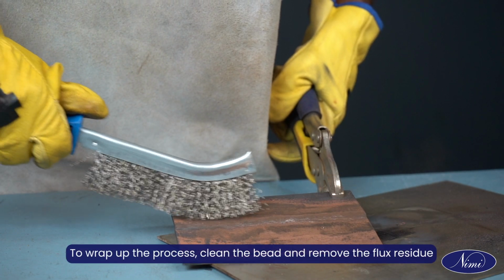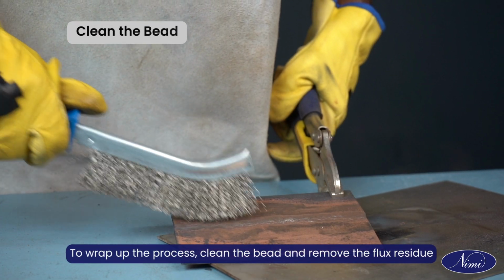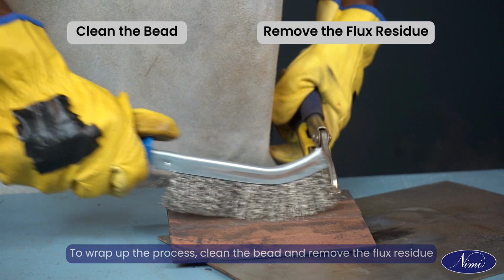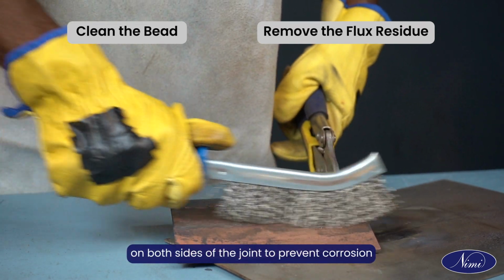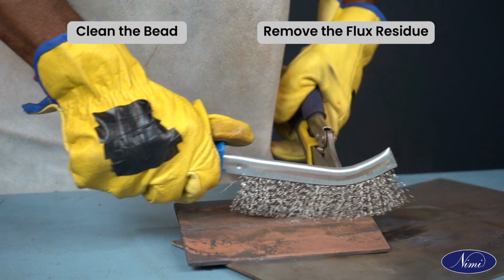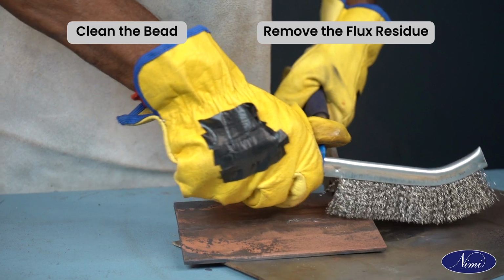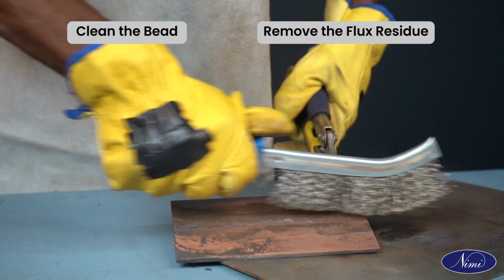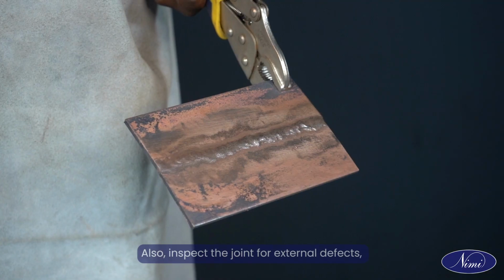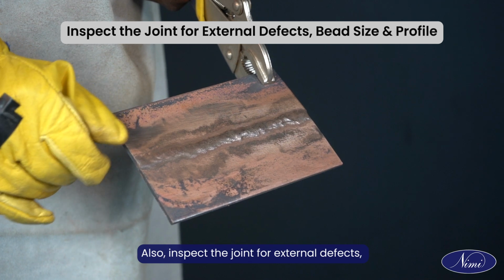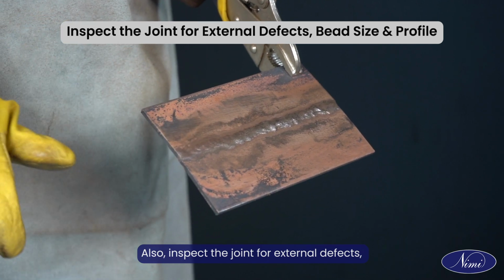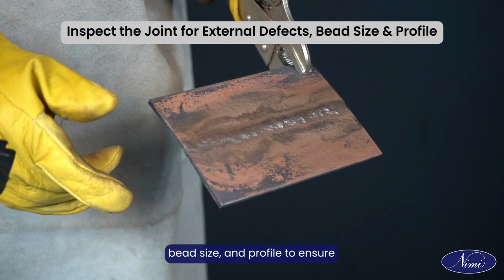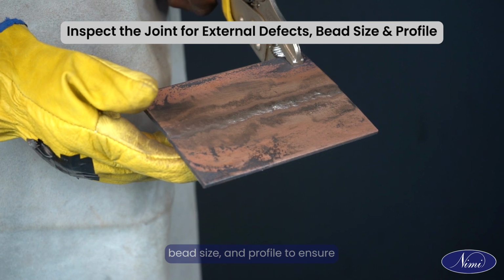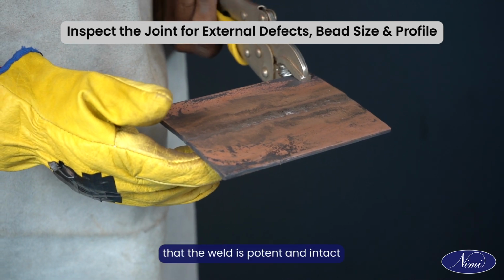To wrap up the process, clean the bead and remove the flux residue on both sides of the joint to prevent corrosion. Also, inspect the joint for external defects, bead size, and profile to ensure that the weld is potent and intact.